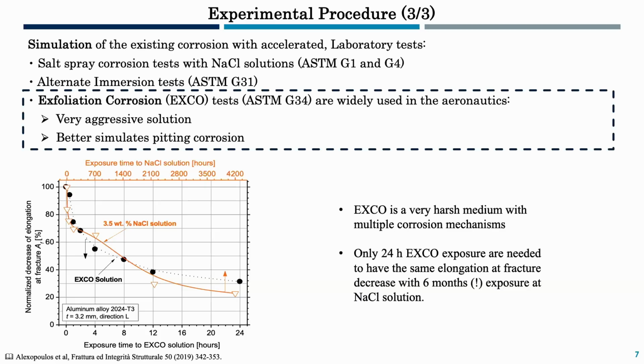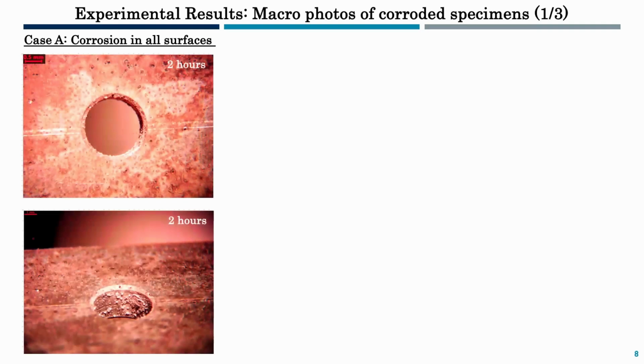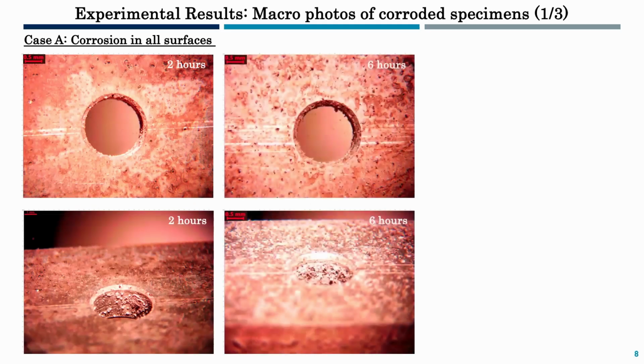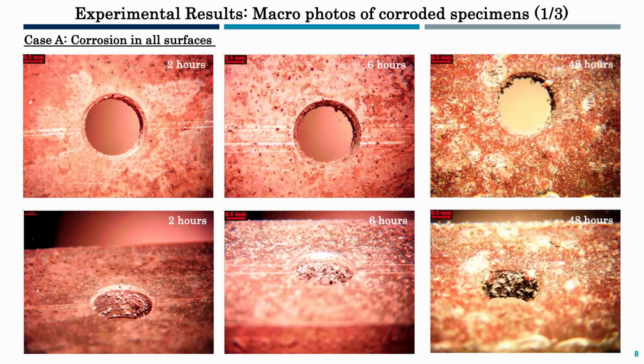So we are moving to the experimental results. Here, some macro photos of the corroded specimens are presented, which show the evolution of surface deterioration with increasing corrosion exposure time: 2 hours, where some pits on the surface are noticed, 6 hours, and the extremely high corrosion exposure time, 48 hours, where exfoliation corrosion is evident on the surface.